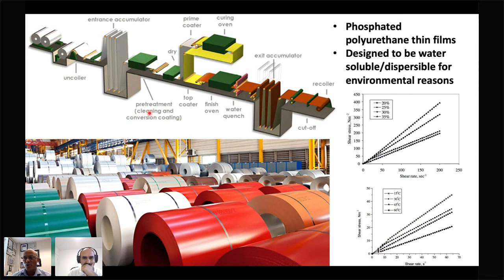And in most commercial treatment lines, oxidizing agents and accelerators are often added, and so the waste is then disposed to the environment. So you would imagine that environmentally it was not a sustainable process. So the idea came to me that the best way to deal with the environmental safety is to get rid of this process. Now, this process also uses chromium as a final stage in the sealing process. And when chromium is disposed into the environment, it becomes a hexavalent chromium, which is chromium-6, and that is a carcinogen.